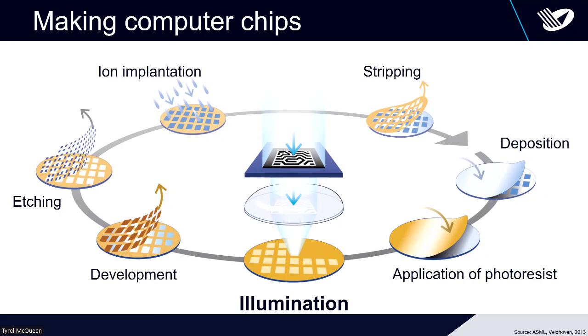This is typically some wet washing procedure, which means that the structures that you imprinted are left behind, and then you can functionalize them. So you first etch structures in, and you can implant ions to get a certain desired electric functionality. After that, you get rid of the resist, and you start all over again. And you can build layer by layer up to hundreds of layers in modern ICs. So this is really this whole process that takes this whole fab where one costs 10 billion with 1,000 steps involved. We've condensed here into a little circle.